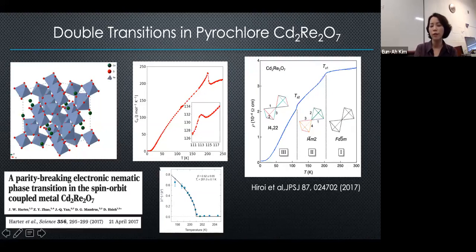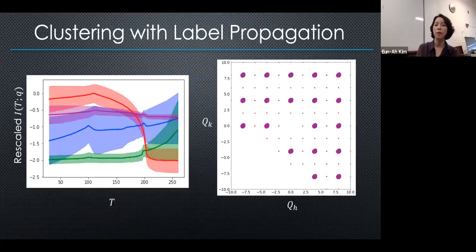Now, it's long been believed that it is a structural transition, likely going from this high symmetry pyrochlore state to a state where the two tetrahedra become inequivalent, with some chirality developing and the bonds within tetrahedra becoming inequivalent. But especially this lower transition is extremely difficult for X-ray to detect because the unit cell size is not changing. It's an example of intra-unit cell order. When we did the clustering, assuming all the reciprocal space points nearby should belong to the same cluster, which is called label propagation, the result we got is on the left-hand side.